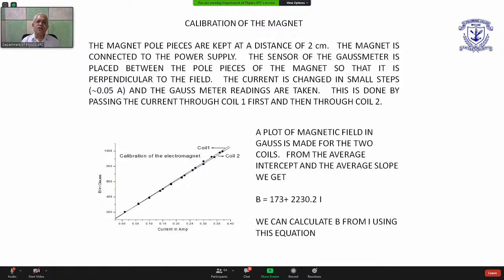The calibration graph is some kind of a fit to the experimental points, and the use of both the coils of the electromagnet gives us a better estimate of the average field at a certain current. Once we fit this graph to a linear equation, we see that the magnetic field can be computed by the equation shown here: B equal to 173 plus 2230.2 times the current I.